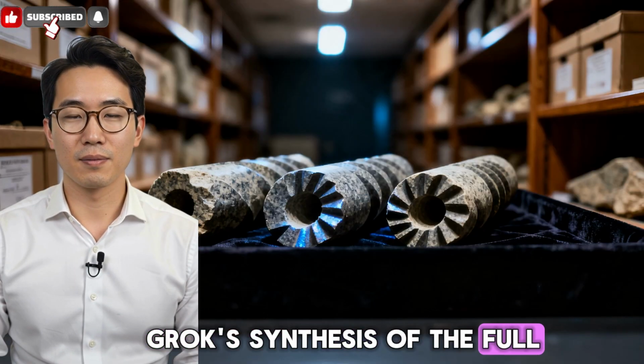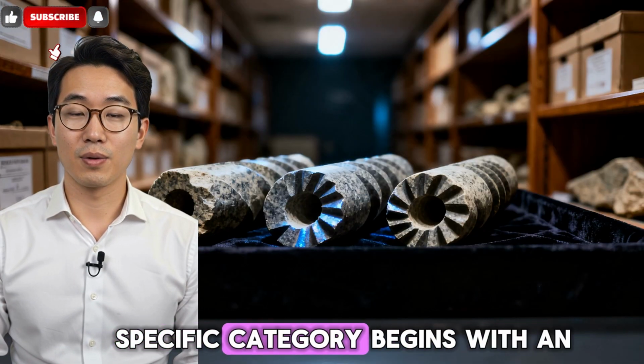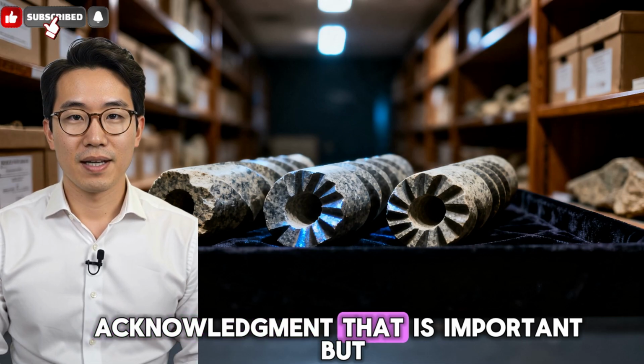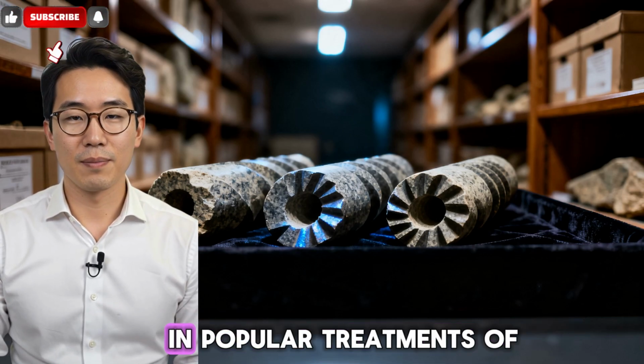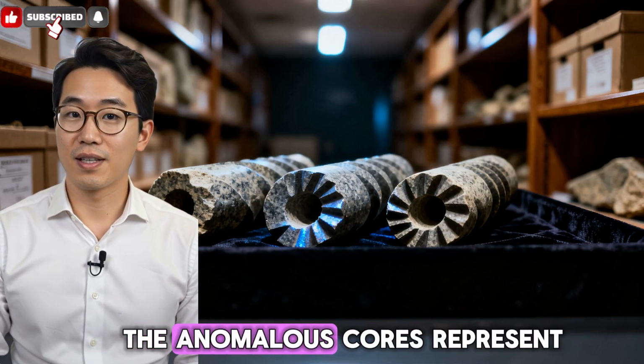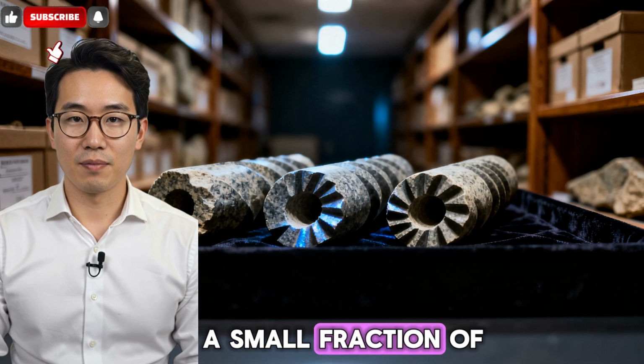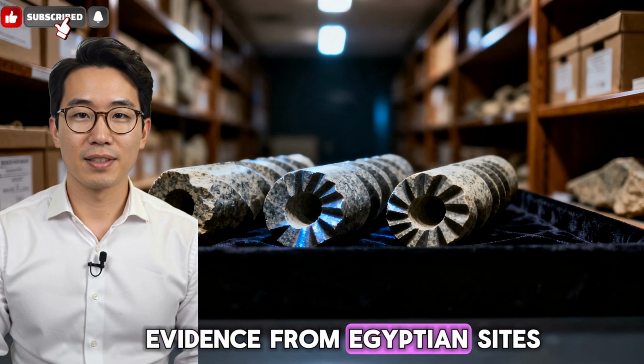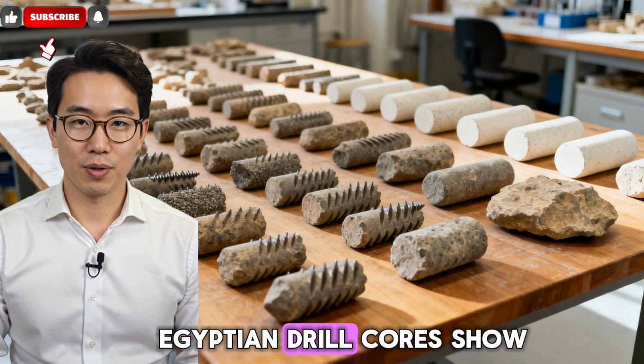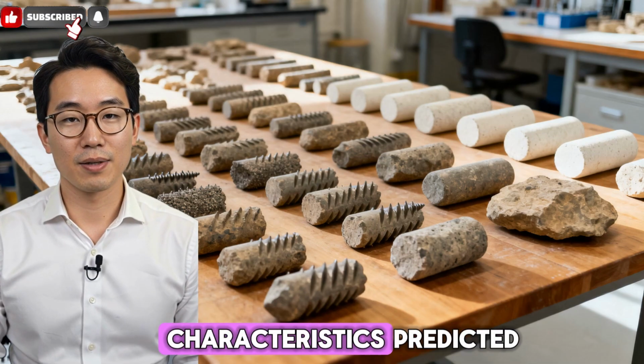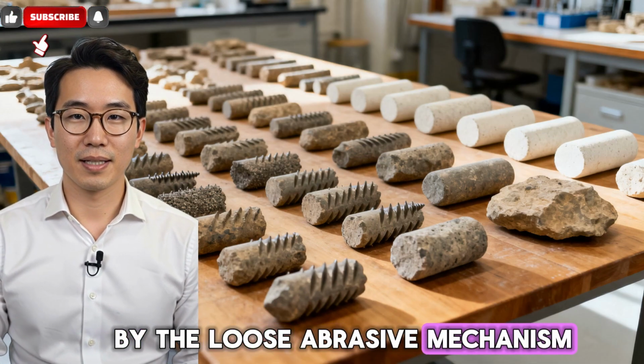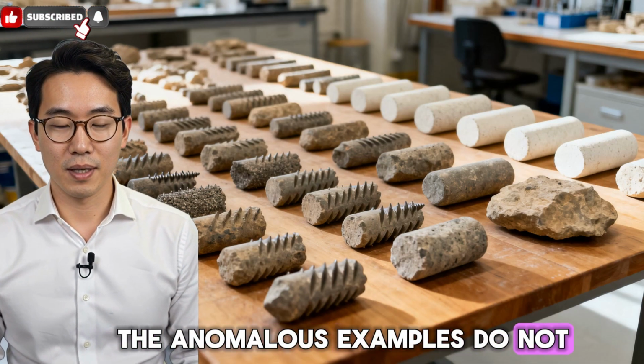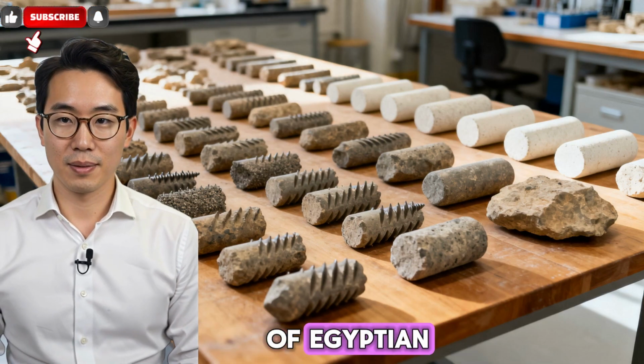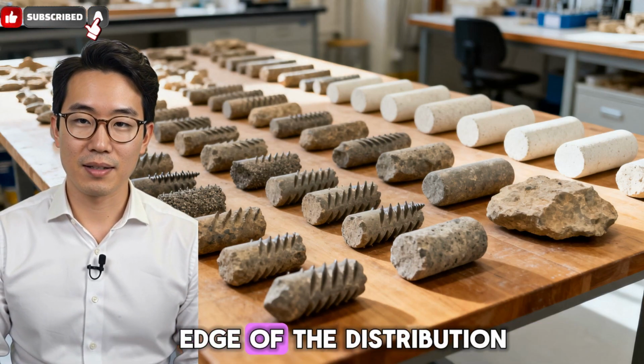Grok's synthesis of the full body of evidence around this specific category begins with an acknowledgement that is important but frequently overlooked in popular treatments of the subject. The anomalous cores represent a small fraction of the total drilling evidence from Egyptian sites. The great majority of Egyptian drill cores show exactly the surface characteristics predicted by the loose abrasive mechanism. The anomalous examples do not represent a different system from the rest of Egyptian drilling. They represent the outer edge of the distribution.